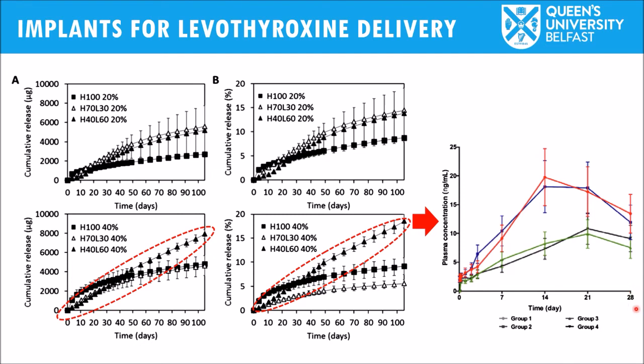More tests need to be done because obviously the dose was not adjusted accordingly to the rats, because the implant would be tiny in that regard. So the results suggested that the implant that will be needed to provide therapeutic doses will be at least 10 times smaller than the ones that we administered to the rats. So that will lead to really small implants, and they will open the possibility of using minimally invasive implanting techniques to apply implants of this size.